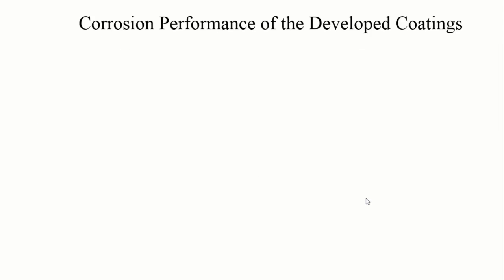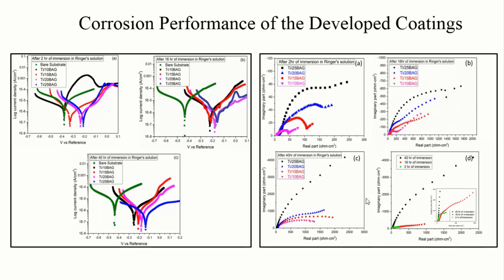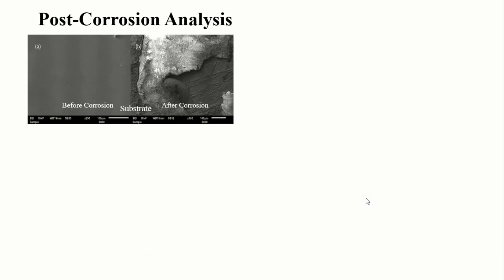Corrosion performance of these coatings and substrates was also evaluated in Ringer solution for 2 hours, 16 hours and 40 hours of immersion time. Potentiodynamic scans and Nyquist plots show that the coatings are successful in protecting the substrate from corrosion. Also, corrosion resistance of the coatings increased with the increment in baghdadite content.